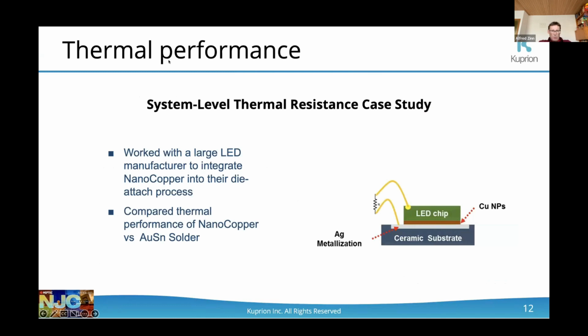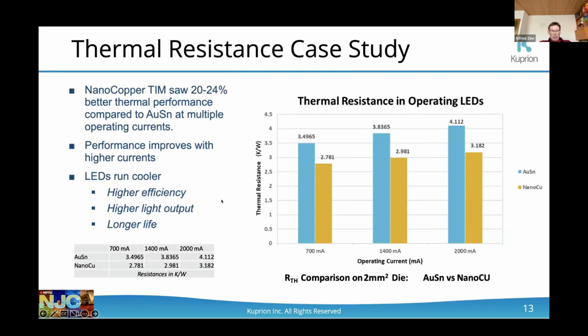So on the thermal performance, we have done a lot of work with LEDs, and want to present here system level testing that was done by an LED company that we have been working together with. So the thermal and the performance of the LED was done on the system level with this setup. And the results were really astounding. We compared it with the standard gold tin solder, the Eutectic 80/20. Same system, same thickness, and we saw a 20 to 25% improvement in thermal resistance, which is plotted here. So you have the gold tin here in blue and the copper in a more yellow color. And it got better and better with higher power ratings. So this is really very, very amazing.